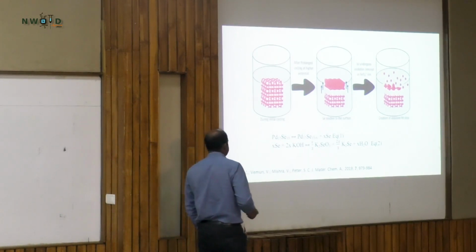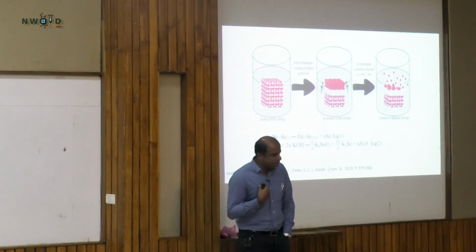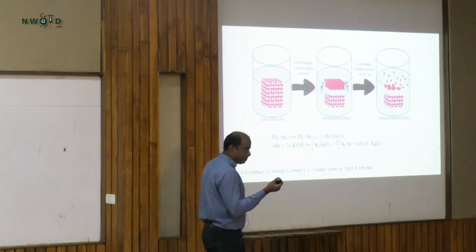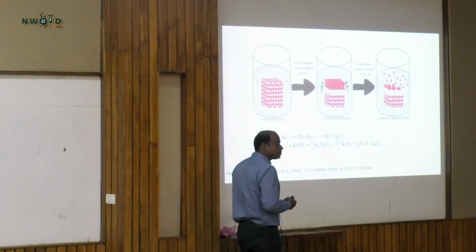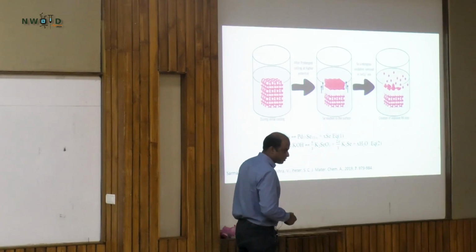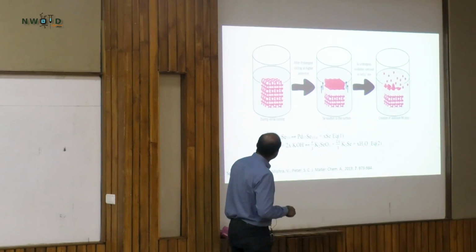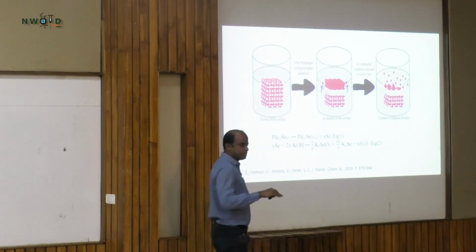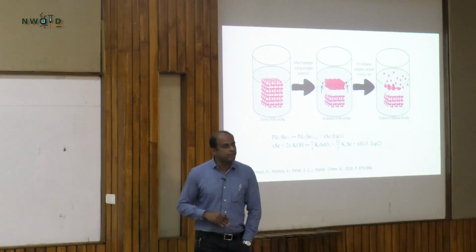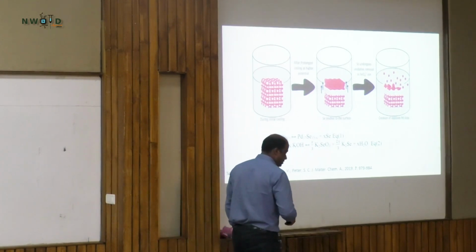At each 10,000 cycles, we took the solutions and did ICP, and we understood that the amount of selenium is slowly building up. That means selenium is coming off from the system, and based on the complete studies we proposed that selenium is slowly etching out of the system and protecting the surface, and keeping the activity of palladium as good as from the first cycle.